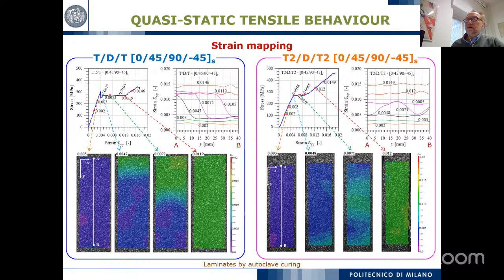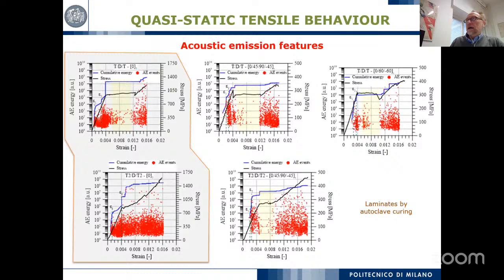But finally, what we observed is that this range of pseudoductility appears also in the thick ply laminate. Moving to some observations with the acoustic emission, this is a recording of the acoustic emission during the tensile test compared to the stress strain curve.